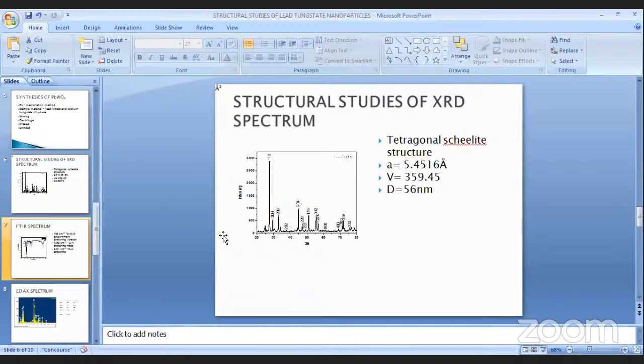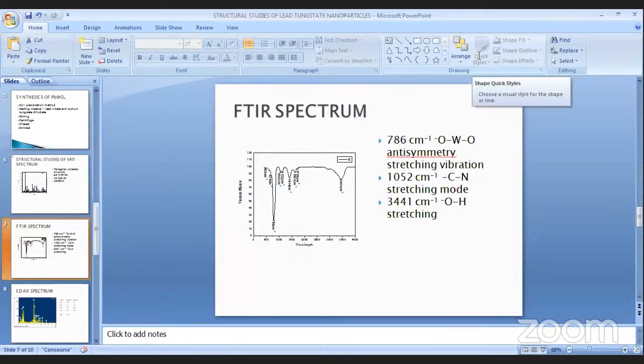The FTIR spectrum has a strong peak at 786 centimeter inverse, the O-W-O antisymmetric stretching vibration. This stretching vibration is because the tetragonal atoms are isolated from one another, and the number of O ions surrounded by the Pb ion is 8. The CN stretching mode is around 1052 centimeter inverse and the OH stretching mode is around 3441 centimeter inverse.